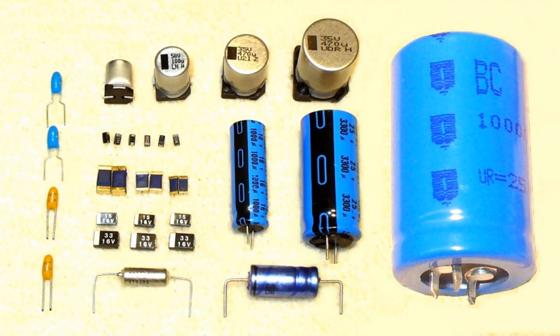The main causes of DCL for solid tantalum capacitors include electrical breakdown of the dielectric, conductive paths due to impurities or poor anodization, bypassing of the dielectric due to excess manganese dioxide, moisture paths, or cathode conductors (carbon, silver). This normal leakage current in solid electrolyte capacitors cannot be reduced by healing, because under normal conditions solid electrolytes cannot provide oxygen for forming processes. This statement should not be confused with the self-healing process during field crystallization. See below, reliability, failure rate.